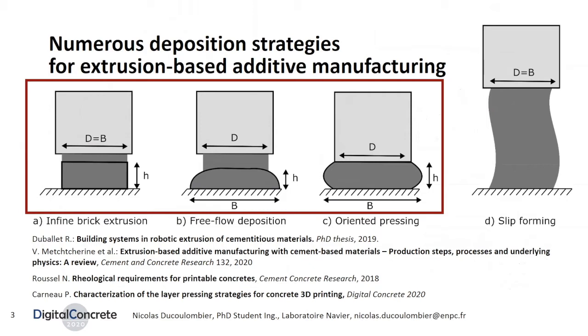Finally, in the third strategy, called oriented pressing, the layer is shaped by the nozzle exit. The layer height is then equal to the distance between the nozzle and the support, while the width is higher than the nozzle diameter and follows mass conservation. This last strategy often allows for better geometrical tolerances, but induces a supplementary force on the sublayer that is roughly proportional to the yield stress. This last deposition strategy has been discussed in detail in the presentation of Paul Carneau, which we highly recommend. As a conclusion, yield stress at the nozzle exit is a critical parameter to properly control the deposition for all different strategies.